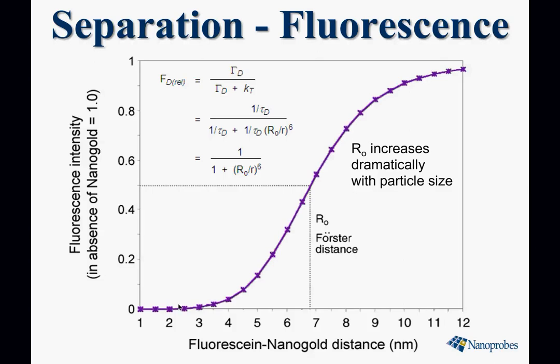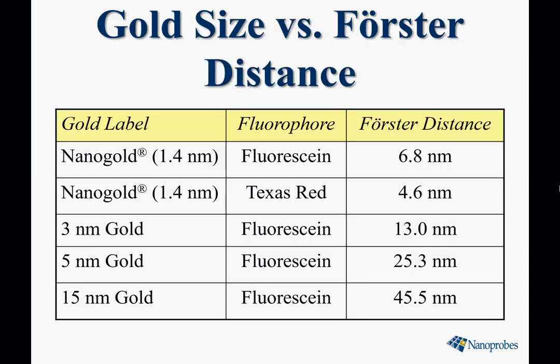This is the effect of fluorophore separation on the degree of quenching. And what we're showing here is separation along the x-axis in nanometers, and the proportion of native fluorescence which is retained at that separation. And the Forster distance, which is defined as the distance with 50% retention of fluorescence, for Nanogold and fluorescein is about 6.5 to 7 nanometers. That distance, the Forster distance, increases dramatically with particle size. With Nanogold, it's 6.8 nanometers. With 3 nanometer gold, it's up to 13 nanometers. With 5 nanometer gold, it's 25 nanometers. And by the time you get to 15 nanometer gold, it's up to 45 nanometers. And that really means you just can't make a combined 5 or 15 nanometer gold and fluorescently labeled immunoprobe.